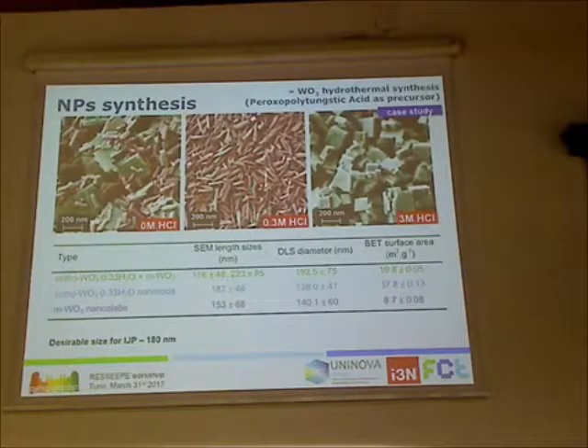I mentioned that we need also to print this, so we also need to take into consideration that the maximum dimension of these particles needs to be controlled in order to pass the nozzle of the printer that will be used to spray the particles on the substrate. So we also need to consider this, we stay below a certain value. For instance, in this case, below 180 nanometers to be compatible with the system that we have.